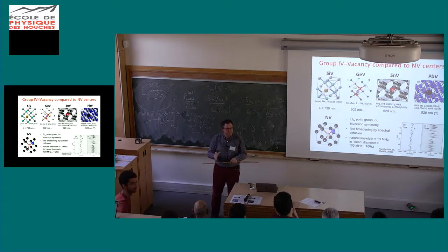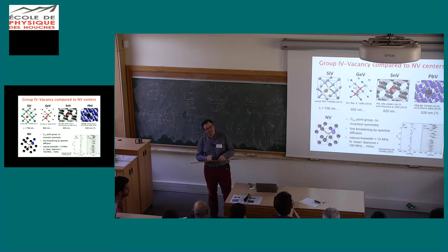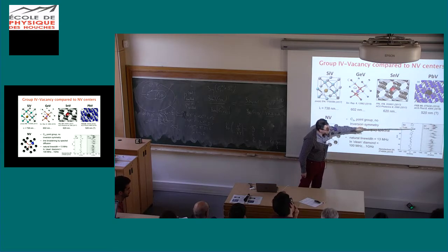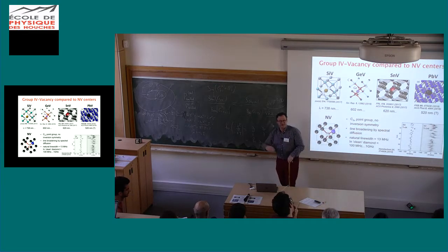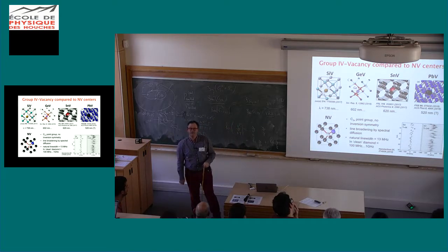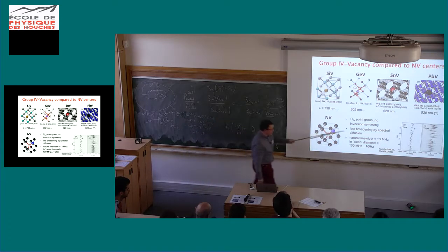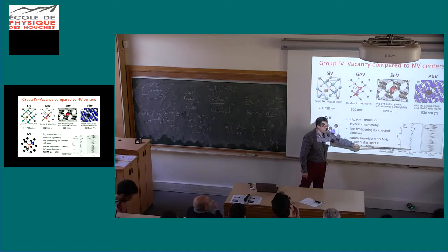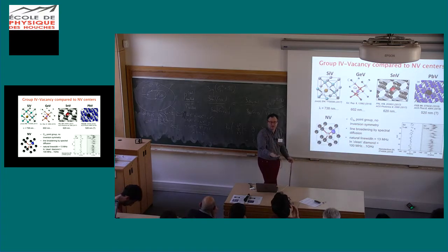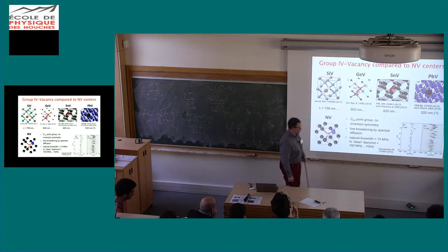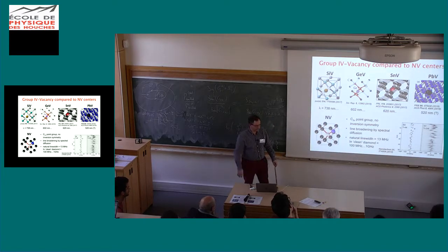These fluctuating charges can modify the zero phonon line, and that will induce this kind of jitter of the line, just a shift of the line due to the fact that, for instance, one electron has come and modified the orientation of the dipole, etc. And also, now if you look at ensembles, you will have a strong inhomogeneous broadening associated to this behavior at the single NV center level. And of course, if you increase a little bit the temperature, this effect becomes more and more important.